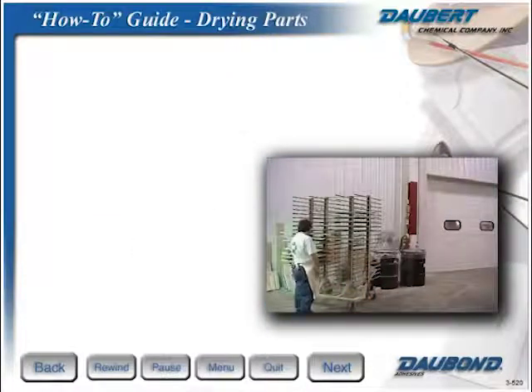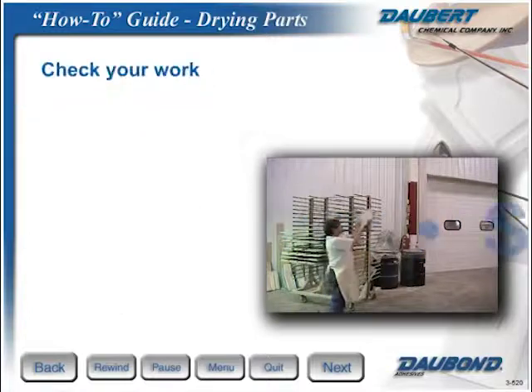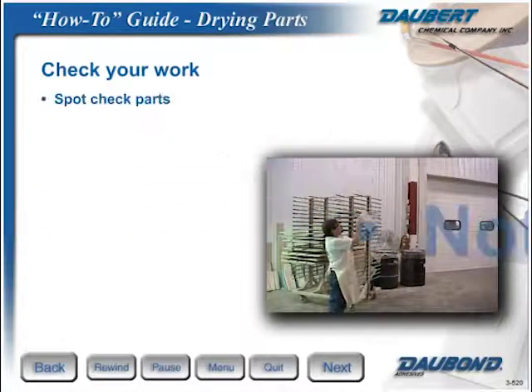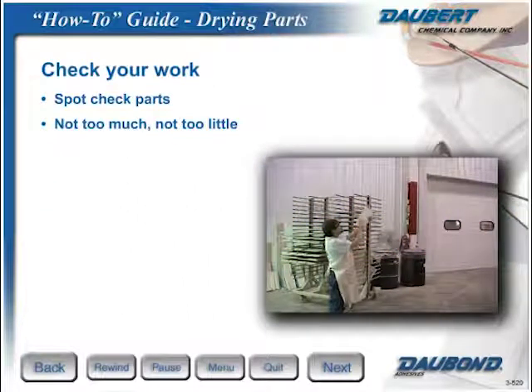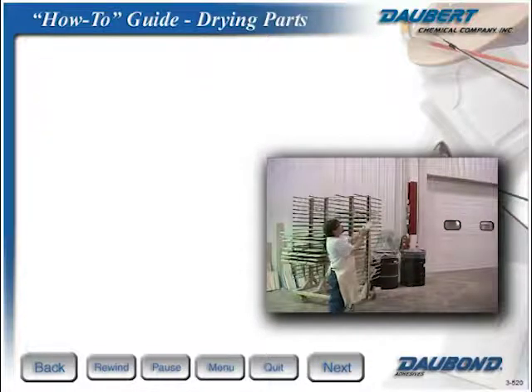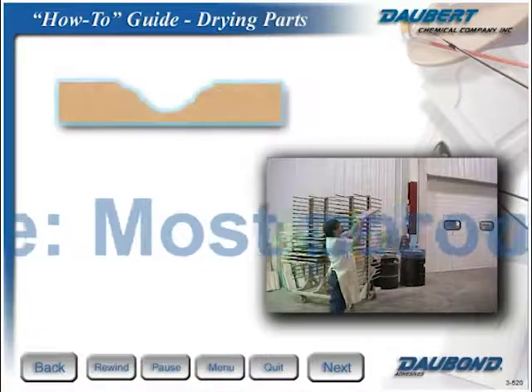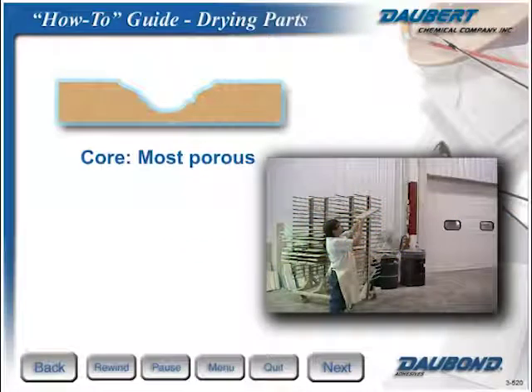Always spot check parts after they have dried to be sure adhesive has not soaked into the board too far. There needs to be enough adhesive to provide a bond across the entire surface, especially the edges. MDF is most porous in the center, meaning it soaks up adhesive here. That's why a gloss check is important.